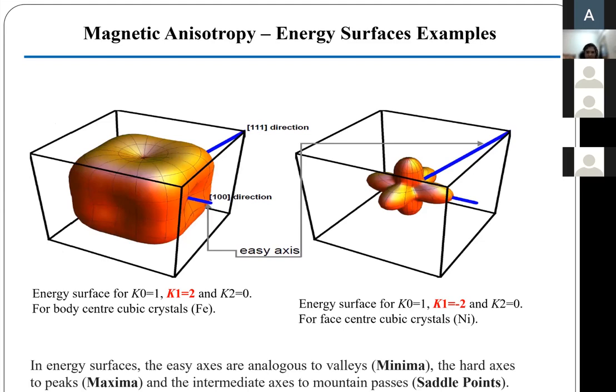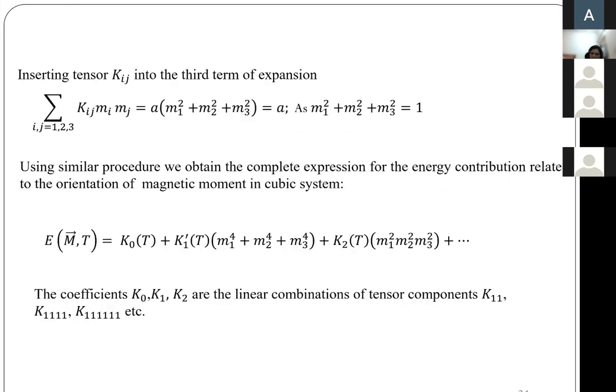Then let's look at the magnetocrystalline energy for different combinations of these values, for example K0 equal to 1, K1 equal to 2, K2 equal to 0. These are progressively the 0 order term, first order term, second order term, and so on. The interplay between these values actually changes the free energy surface. When I say free surface, in the absence of any magnetic field, we don't apply any magnetic field, we just plot the energy on its own. So we just plot this term on its own, the first 3 or 4 terms.